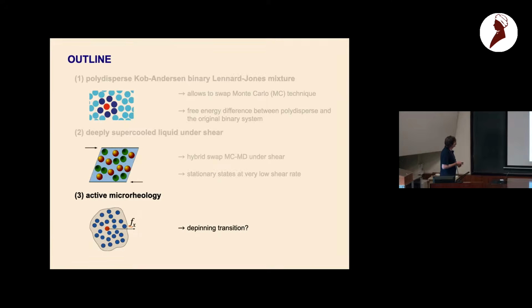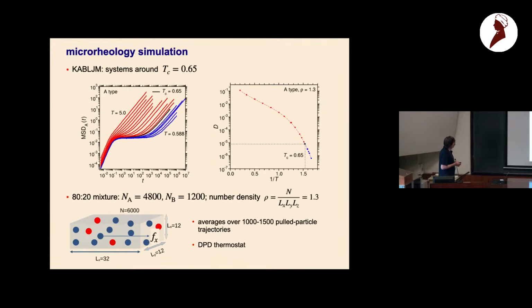Okay, now I come to active microrheology. First of all, here we go back to the original binary Lennard-Jones mixture. So this is just MSDs for the Kob-Andersen mixture, and from this the self-diffusion constants as a function of inverse temperature.